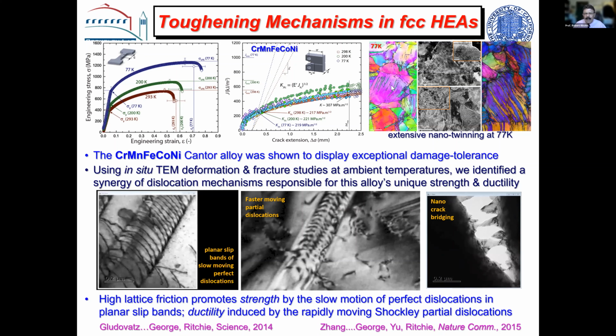And this was one of the ones, this was known as the Cantor alloy. It's a chromium, manganese, iron, cobalt, nickel, equiatomic, face-centered cubic, although each of these elements has different crystal structures. When you look at these alloys, I'm sure you've seen this story before because it's quite old now, but we look at the engineering stress strain curve. This is at room temperature, this is at dry ice, and this is at liquid nitrogen temperature. And these alloys get harder and they get more ductile, which of course would be unusual for a body-centered cubic, but the degree at which this happens is quite unusual for a face-centered cubic.